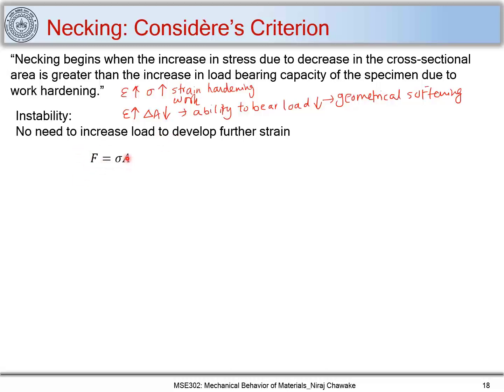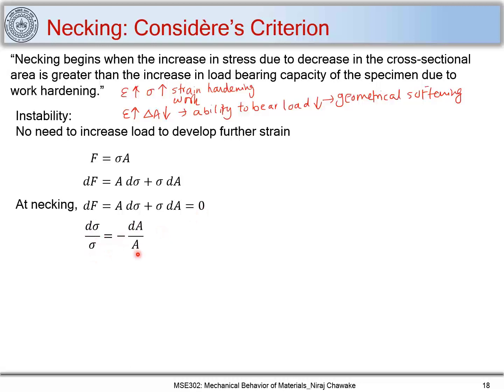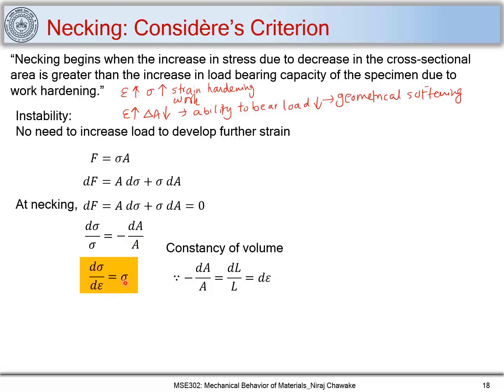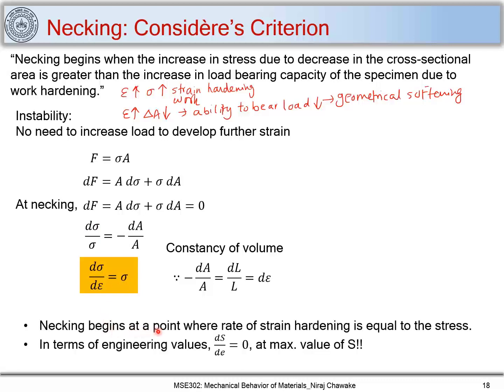Writing force as F = σ·A and taking the total differential, at necking dF = 0, giving dσ/σ = −dA/A. Applying constancy of volume just before necking, −dA/A = dl/l = dε. Substituting, we get dσ/dε = σ. This means necking begins at the point where the rate of strain hardening equals the instantaneous true stress. In engineering terms, necking begins where dS/de = 0, i.e., at the maximum value of S — the UTS.